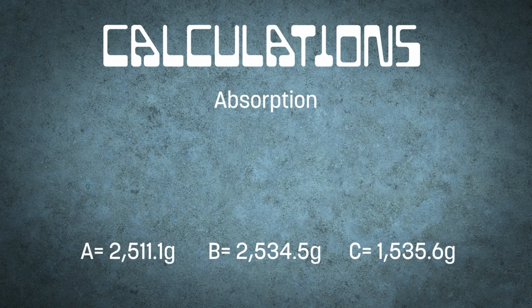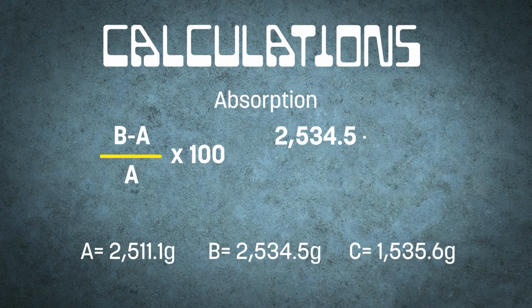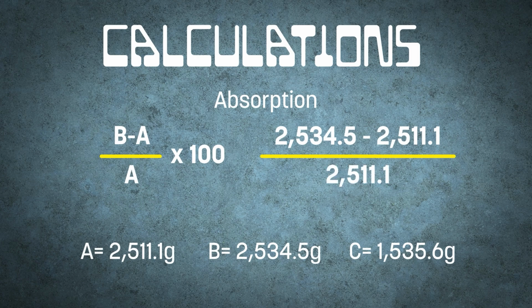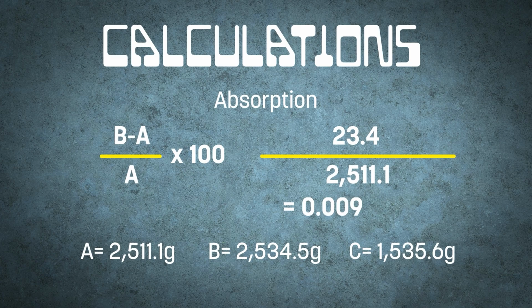We can now go ahead and calculate our absorption. The calculation for absorption is B minus A divided by A times 100, or 2,534.5 minus 2,511.1 divided by 2,511.1 times 100. If we calculate this out, we should get 23.4 divided by 2,511.1, which comes out to be 0.009. Multiplied by 100 gives us an absorption of 0.9%.